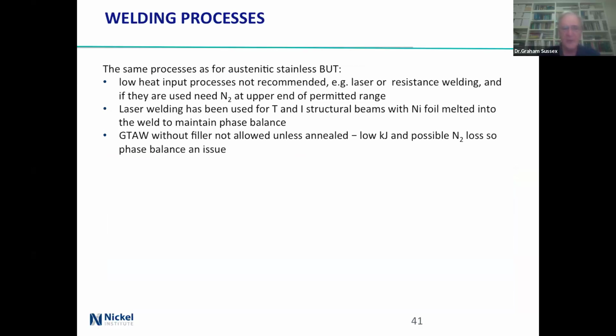Okay, same processes as for austenitics. Lower heat input, not recommended. So if you're using laser or resistance welding, well, if they need nitrogen at the upper end, yes, that would work. Resistance welding, yeah, okay. How do you avoid it? Well, yes, you can flood it with nitrogen. Laser welding has been used for T and I structural beam, putting a nickel foil in it, but it was a difficult process, so it tends not to be used now. And GTAW without a filler is not allowed unless you're going to anneal it, because of low kilojoules, possible nitrogen loss, and so your phase balance would be an issue.